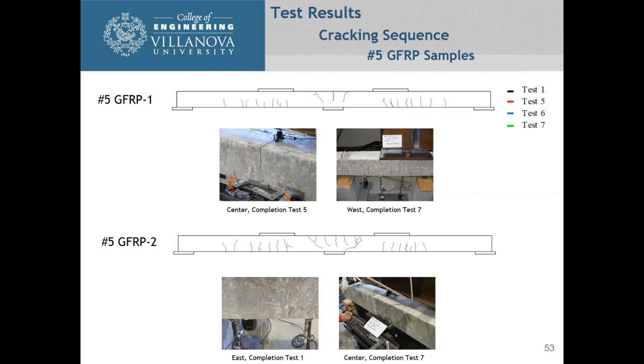And now we're loading it to failure in test 6, and you can see the cracking that was exhibited. A lot more cracking in the positive area. Those are flexural cracks. And again, you can see what looks like shear cracks developing at the negative moment area. You have the flexural cracks here, but now you have diagonal cracking essentially coming from the load going to the points of support. And in test 7, we just saw an increase of the length of all these cracks, but nothing substantial failures.